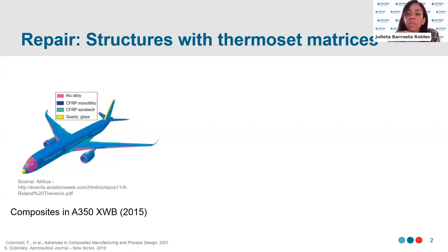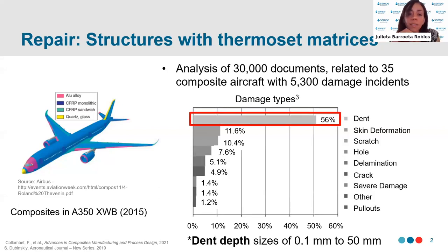To start my presentation, we know that composite materials with thermoset matrices such as epoxies have been used in aerospace for quite some time. One example of this is the Airbus A350, as can be seen in the slide. It is inevitable that when these aircraft are in service, they're going to encounter damage. There have been studies that analyzed over 5,000 damage incidents, and researchers found that 56% of these damages were dents, with sizes ranging from 0.1 up to 50 millimeters. Other damages observed were skin deformation, scratches, holes, delaminations, and cracks. The rest of the damages were less than 1.4% of the incidence rate observed.